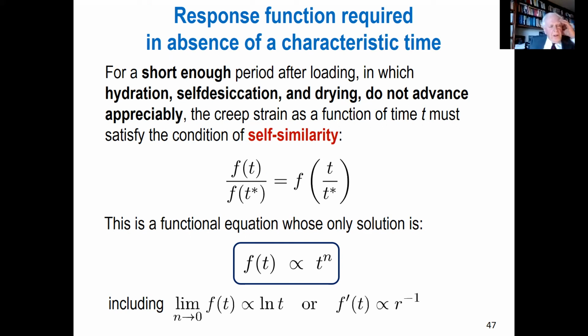So theoretically, we know well the asymptotes, short time as well as long time. So you take short time, there is no characteristic time, which means that in a response function, any response function, if we take one or another characteristic time, we must get similar behavior, which leads to this functional equation. That functional equation happens to be easily solved. There is only one solution, and that's a power function with some exponent n. Please note, a limit of power function is logarithmic function, which is a power function of rate, so that's also admitted.